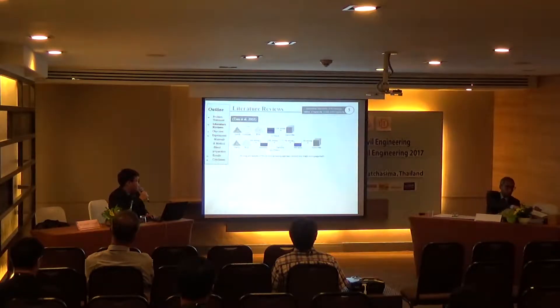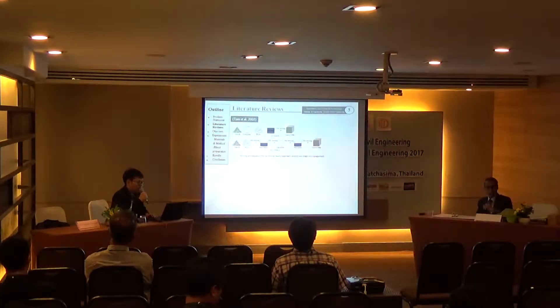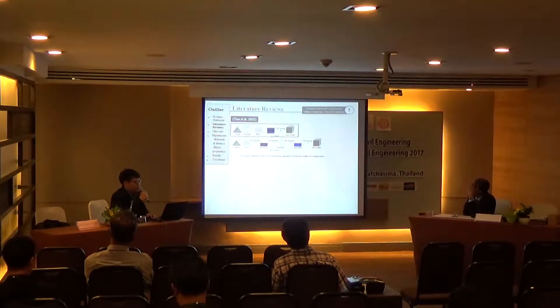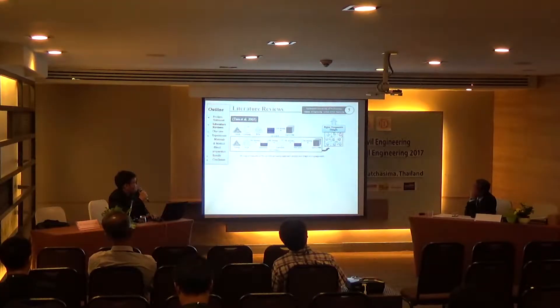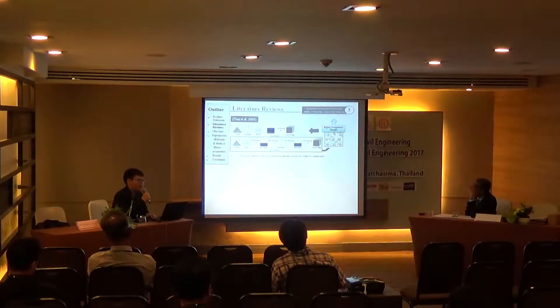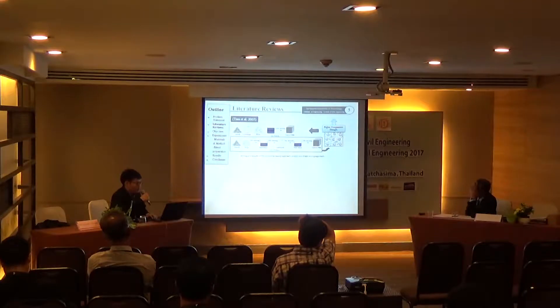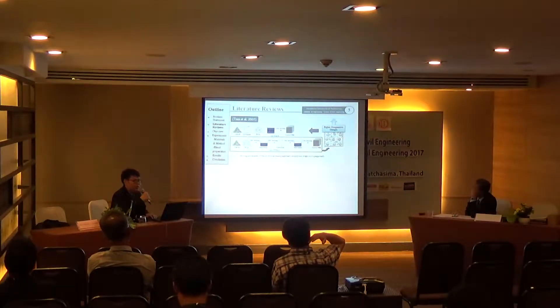The next one is TAM. He proposed a new method to mix RCA concrete called the two-stage mixing approach. As seen in the blue box, the normal mixing approach is different from the two-stage mixing approach as seen in the green box. From this new approach, the compressive strength of the RCA concrete may be higher than with the normal mixing approach. By the two-stage mixing process, it can fill up some pores in the RCA, resulting in a denser concrete that improves the interfacial transition zone.